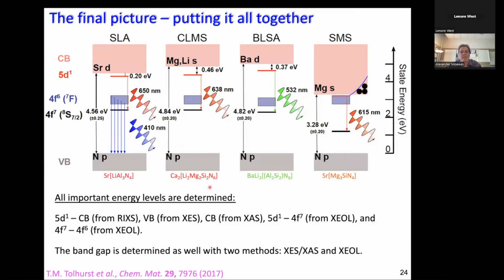And then we also know, of course, the conduction band from XAS, which we probe. We know the valence band from X-ray emission. And we even know from XEOL also the 4f7 and 4f6 level. So bottom line is, what you need to know for this kind of research is where all these orbitals lie.